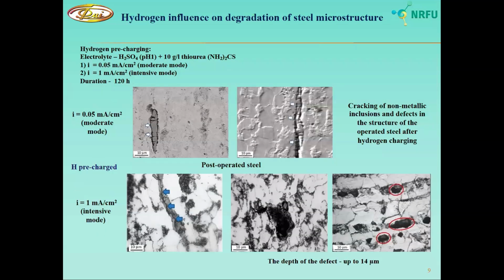To study hydrogen influence on steel microstructure degradation, specimens were subjected to electrochemical hydrogen charging under different modes, moderate and intensive, using different cathodic current densities, which differ by 20 times. And also the duration of cathodic polarization was 120 hours, high enough to ensure a more uniform distribution of hydrogen in a cross-section of specimens.